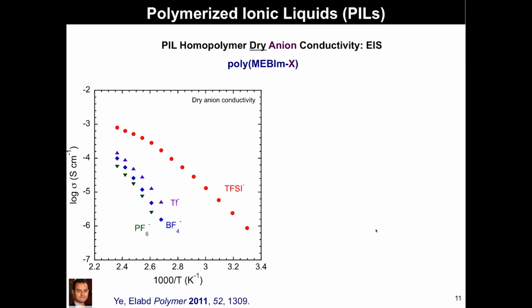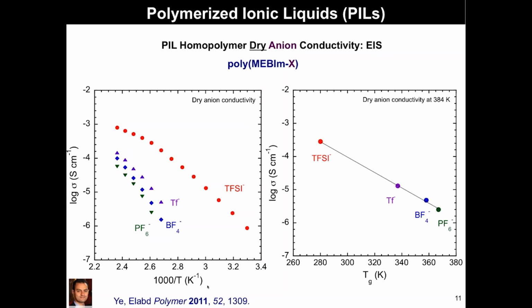And then slide 11, you can see for the fluorinated anions that are hydrophobic, you could plot the ionic conductivity, and this is a property that would be of very high interest for batteries here if you couple this with lithium salt. You can see the properties of the ionic conductivity as a function of the inverse temperature of different counterions here. And again, as the glass transition temperature is lower and lower, that will increase the conductivity. So this is all done under a dry state where the ion mobility of these single ion conductors is very much dictated by the segmental motion of the polymer.